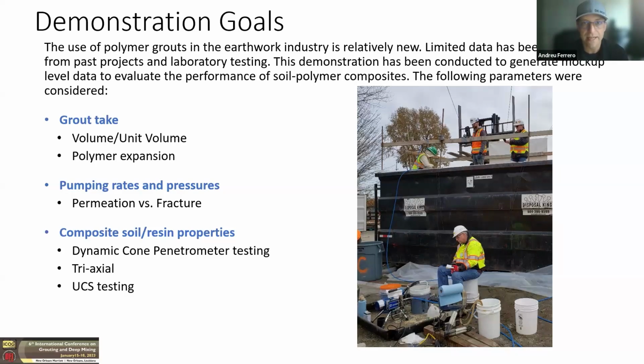with local silty sand, and then we injected that compacted and moisture-treated sand with a polyurethane resin and an acrylate resin. The intention here was to monitor the grout take, monitoring the volume of grout injected per unit volume of soil treated, monitoring the polymer expansion within the soil that we were injecting into, monitoring the pumping rates and pressures so we could determine the permeation versus fracture pressure in this type of soil.